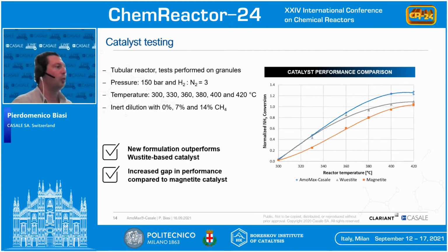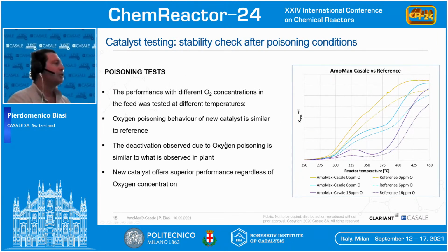But to implement the catalyst, you go to the pilot phase, or you try to understand how to implement at lab scale some new technologies and some new types of testing to avoid the pilot plant. So first of all, as I mentioned at the beginning, poisoning is really important for the ammonia synthesis catalyst. We did some preliminary work understanding the effect of poisoning by oxygen, water, carbon monoxide and carbon dioxide, and they were pretty similar. So we decided to work with oxygen, at a low concentration.